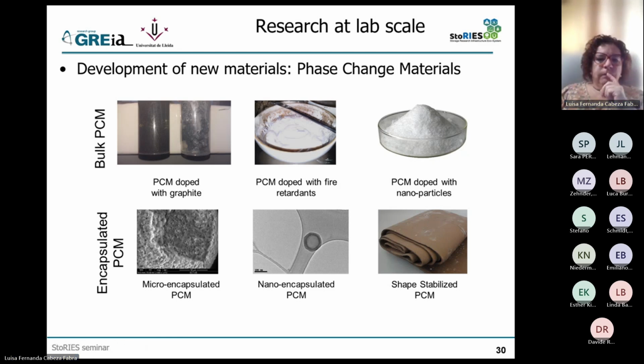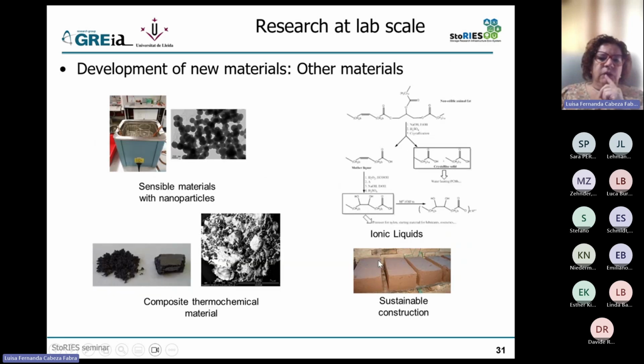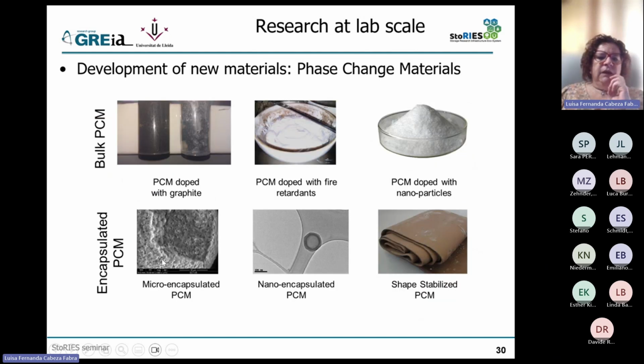And then I also discussed encapsulation. You have some examples. The first one is a microencapsulated PCM. The second one is a nano-encapsulated PCM. And the third one is this shape-stabilized PCM. Here, as you can see, at the end, I have a material which is a polymer. And what we've done here is to put the PCM distributed to give this energy density to this new polymer. But at the end, we call it shape-stabilized because it's a material itself with a shape that, when the PCM melts, it's not a liquid, still the same material with the same shape. Maybe it can be a bit softer. And here again, the challenge is to ensure that there is no leakage.